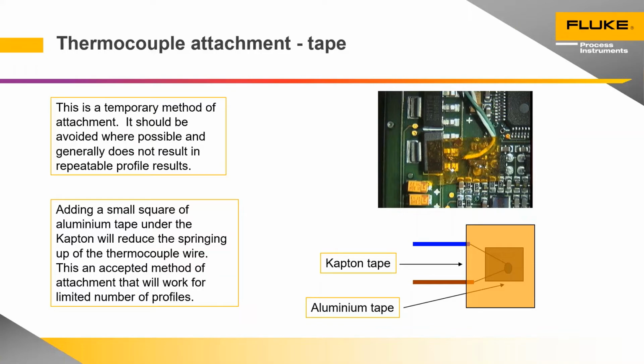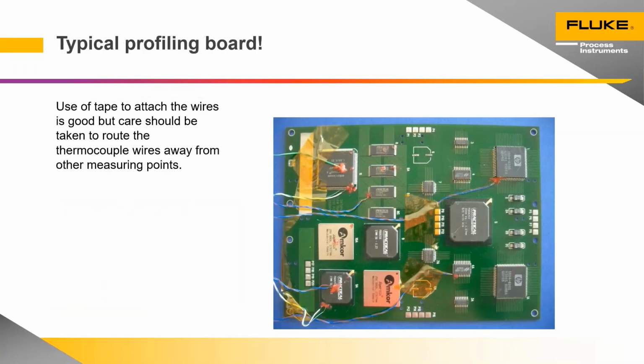If you've got 6 or 10 thermocouples on a circuit board, probably one of them will lift as you go through if you're using this method. It can be improved by using small squares of aluminium tape underneath the high temperature tape. There's articles you can find on the web proposing this method. Just be careful, again, you're going to be measuring the temperature of the aluminium tape junction to the thermocouple, so be very careful to make sure that tape is well pressed onto the legs of the device you're trying to measure. So it's acceptable, but just be very careful when attaching using this method.